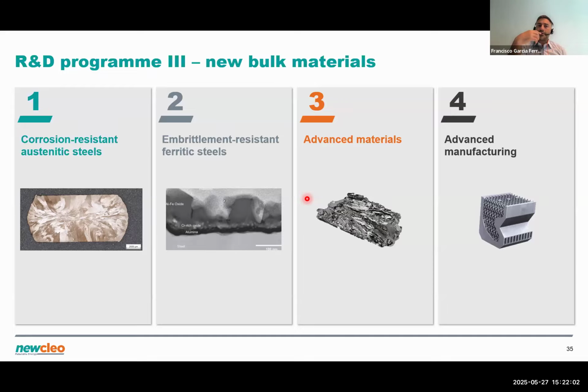Then we have a second pillar on ferritic steels. Ferritic steels are very interesting because they do not swell, and generally, at least in lead bismuth, they have been considered to be prone to liquid metal embrittlement. This is not so strong an effect in liquid lead. Nevertheless, it remains kind of the key research direction one can take if one is working on ferritic steels. In general, their corrosion behavior is a bit better, but one needs to be careful about the embrittlement part.